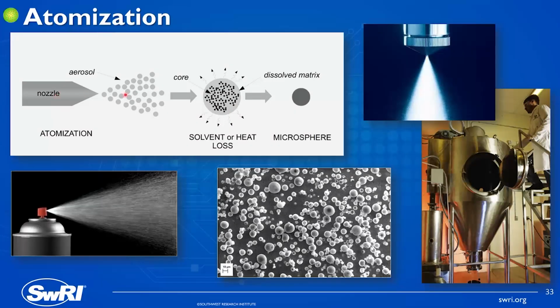If your liquid is a wax, you spray this into a cold chamber and you pull the heat out. So in spray congealing, you're pulling the heat out, or in solidifying, spray drying, you're putting heat in to evaporate off. You get really nice small particles, single tens of microns. Various commercial equipment available from lab scale, and then of course this is the most production you'll see. So tons per hour in terms of quantity on the larger scale, mainly for something like milk powder. So that's atomization, great for matrix particles.